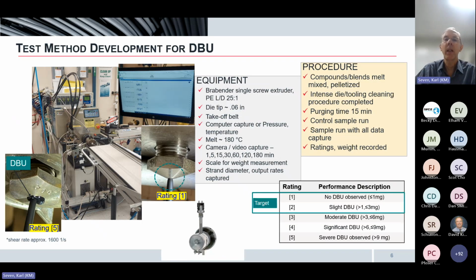Okay, so the first part of all of this work was to basically ensure that we had an effective test method to evaluate die lip buildup. So here I'm describing at a high level what this method was. This consists of a single screw extruder with a typically relatively small die tip, 0.06, where we captured pressures as well as temperatures, and of course the die lip buildup over time. The die lip buildup is captured at set time periods up to 3 hours overall.